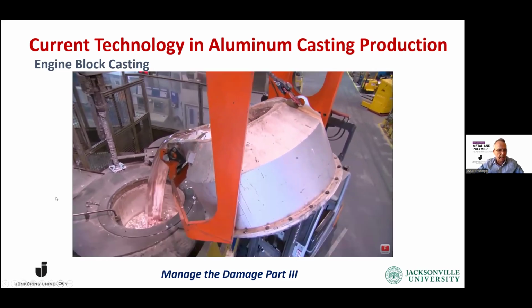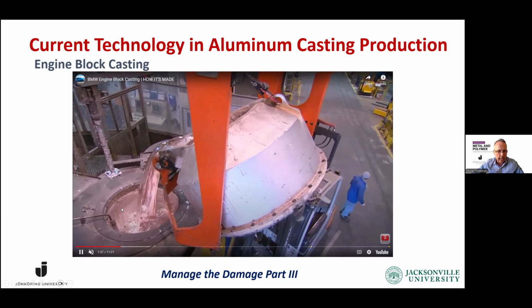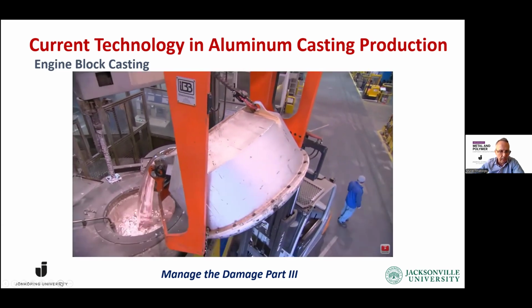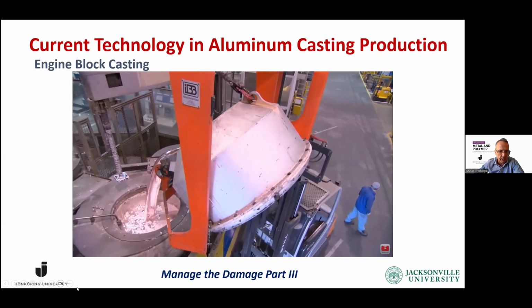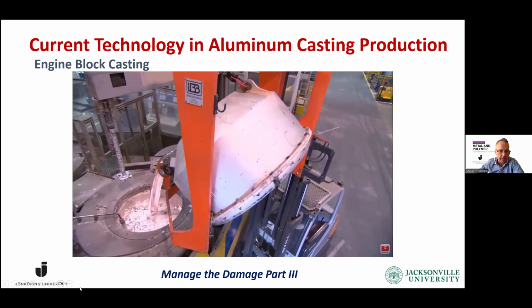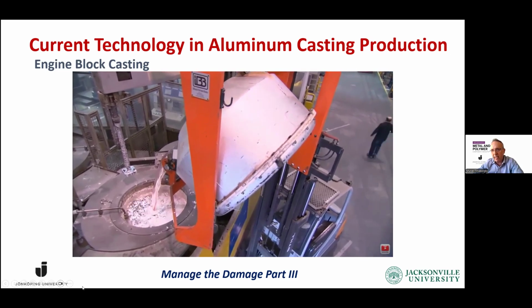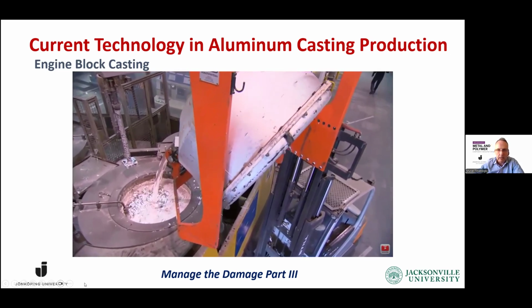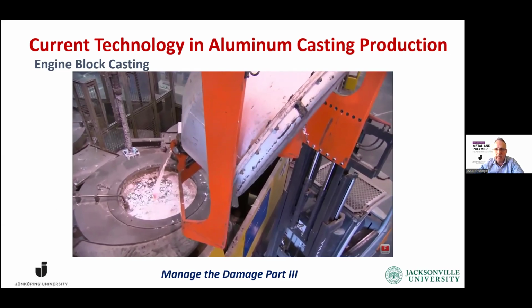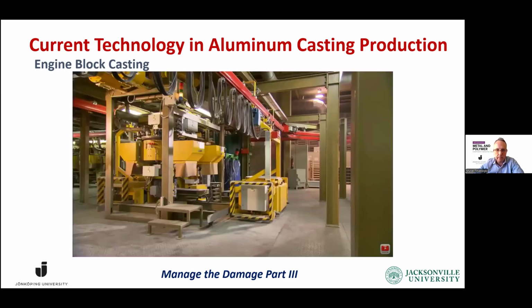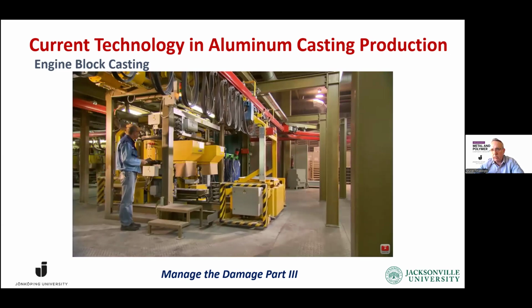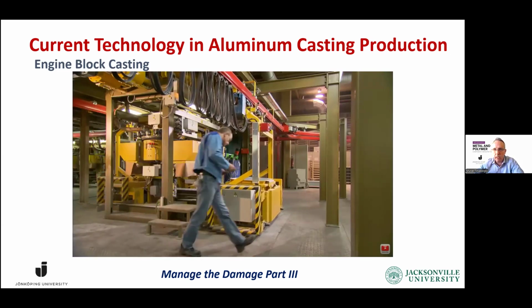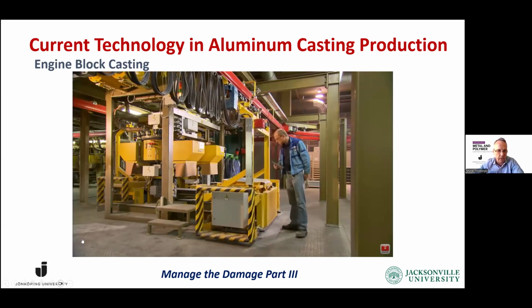And please notice the top of the liquid metal. As you see, it's quite turbulent, and a lot of air has been entrained, a lot of surface covered by an oxide. So this is a perfect way to damage melts. And this all comes from our design of the production system. If we have a central furnace that requires not one, but two melt transfers, every time we do a melt transfer, we seriously damage our metal.